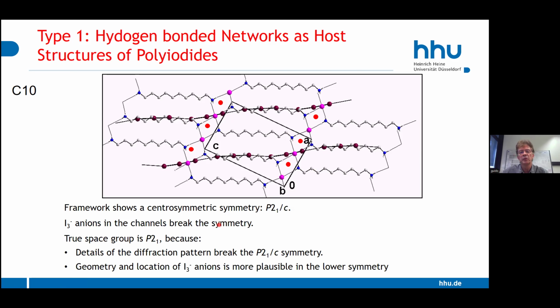And why are we so pretty sure that it's really this lower space group? First of all, the diffraction pattern shows some features that only fit with the P21 space group. But the more important point is that all I3- ions have a normal, typical geometry in the lower space group. If you go to the higher space group, you always have a lot of problems. They are distorted. And also a take-home message for all these cases is, if the structure still has some geometric problems which are unexpected, which you didn't expect for this molecule, it could simply be a crystallographic problem. Okay, so we have seen C8, we have seen C10.